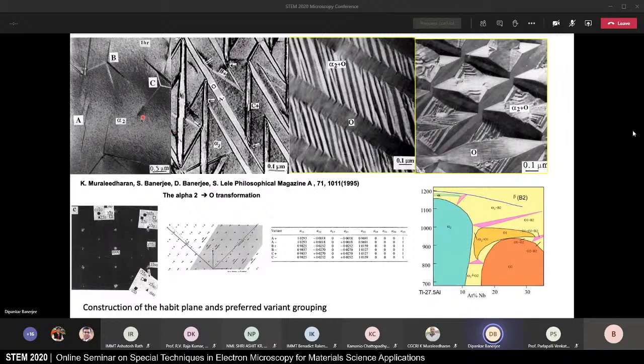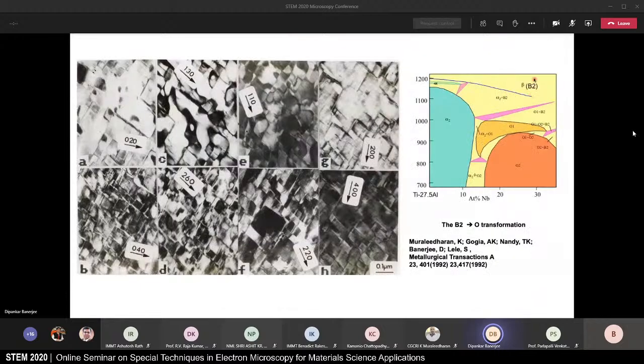And what it shows you is the very complex but very unique microstructures that evolve as a consequence of this transformation. Analyzing these microstructures involved understanding the complexity of this diffraction pattern, the variant distribution associated with this diffraction pattern of the Ti2AlNb phase that forms as these plates in the matrix. It allowed the analysis of groups of variants that formed experimentally, and it involved the analysis of the shape strain associated with each of these variants and how grouping of these variants could minimize the overall elastic energy of the system. Murli also looked at the transformation from the parent BCC phase to the ordered Ti2AlNb phase.